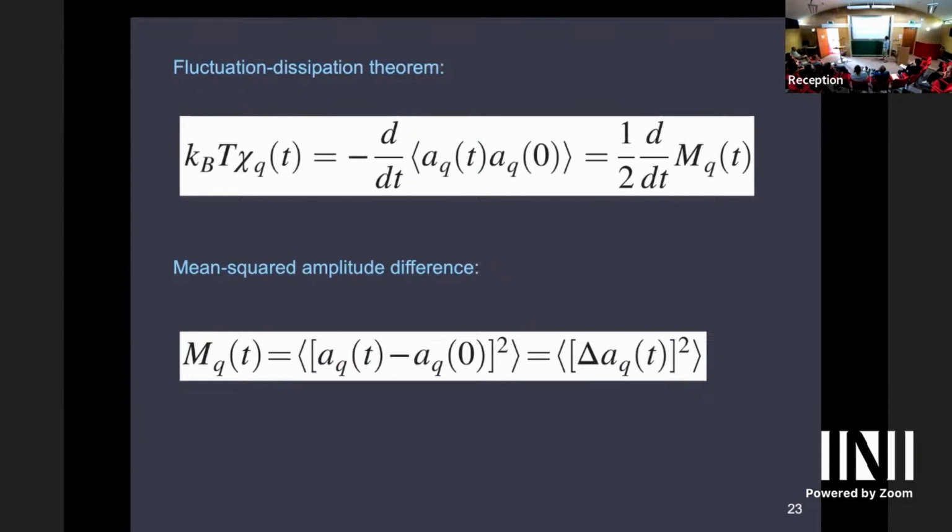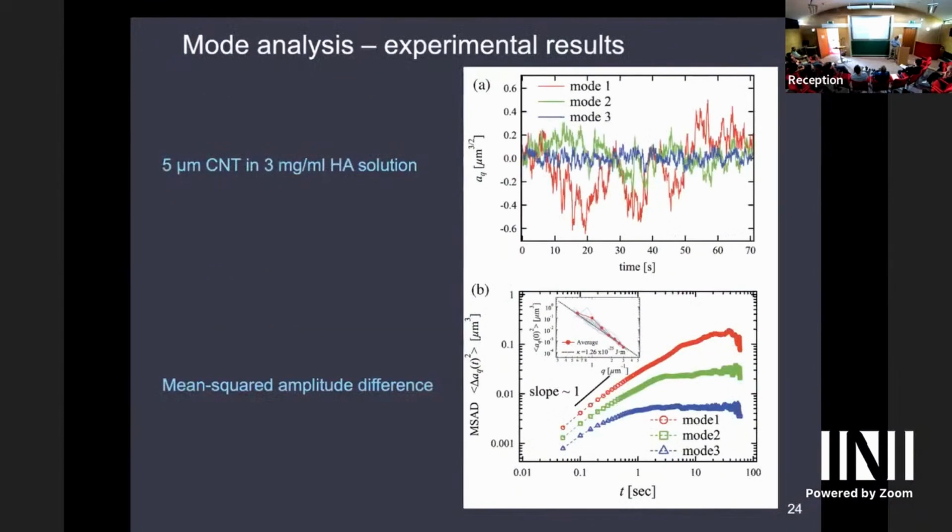Of course, this mean square displacement function is just the difference between the amplitudes compared to the resting, or the starting, amplitude. Like this is a correlation function, and then we can plot that and evaluate that and calculate the G prime and the G double prime, and get done with that.